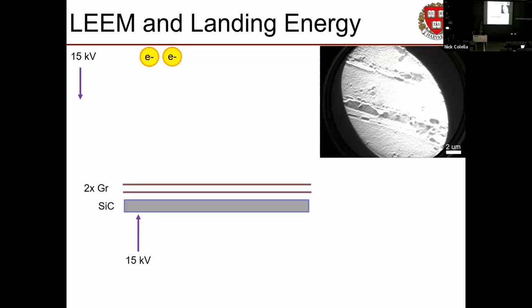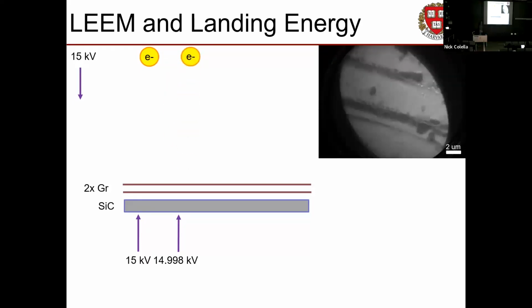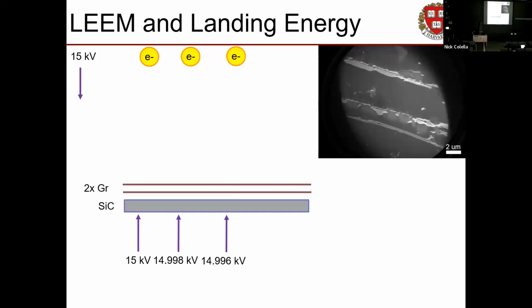But what if we were to turn down the voltage on the sample a little bit? Just 2 volts less on the sample. Now, the electron's not going to slow down quite as far away. It's going to go a little deeper, and we're going to start to get some actual contrast. And in fact, if we keep turning down the sample energies, turning up the landing energies, we probe deeper and deeper into the sample, and we start to interact with deeper and deeper parts of this material stack.